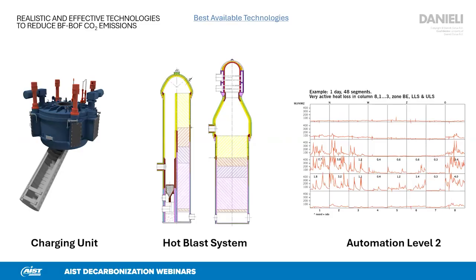The second is to adopt modern hot blast stoves with a hot blast temperature of 1200 degrees centigrade instead of the more conservative 1100 degrees centigrade. And last but not least, by implementing modern state-of-the-art automation level 2 systems, including, as an example, heat flux monitoring to reduce the heat losses by gas flow along the reactor.